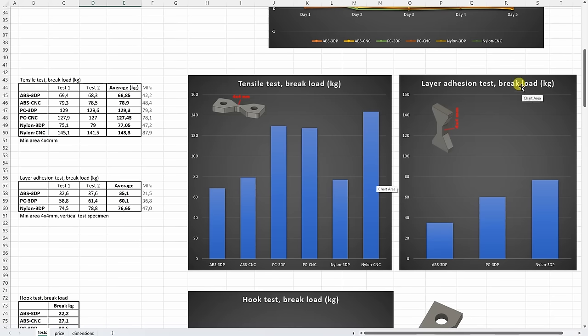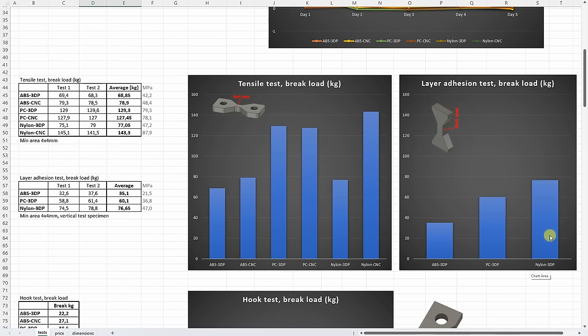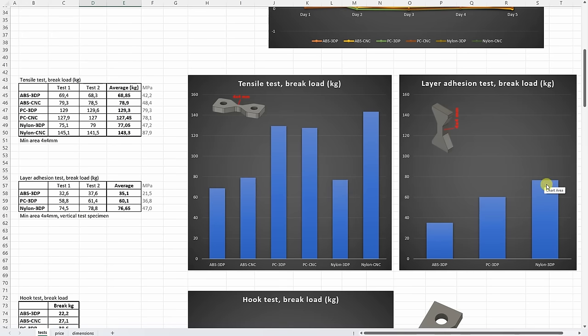Now the layer adhesion test, and I have this only with the 3D printed parts. All three values are very impressive actually. But look at this. On nylon, basically we don't have the weakness in the layer adhesion. These two values are very similar. Of course, don't forget this is printed with SLS technology.